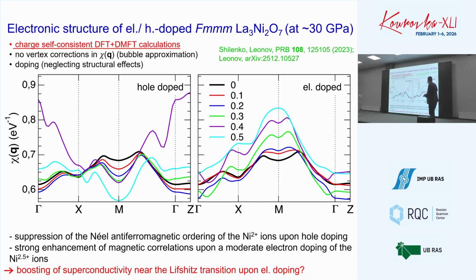As soon as we dope the nickel 2 plus ion with holes, we go in this direction somehow. We get some kind of two competing states, incommensurate competing states, and I interpret this behavior as some kind of stripe phase, a spin charge density stripe state. It ends up at zero. This is nickel 2.5 plus ion. This is some kind of superconducting state. I mean, with this very simple, very naive consideration, we can interpret that if we dope this system with electrons, we raise magnetic fluctuations in this system. Possibly this is the way to tune superconductivity in this material.